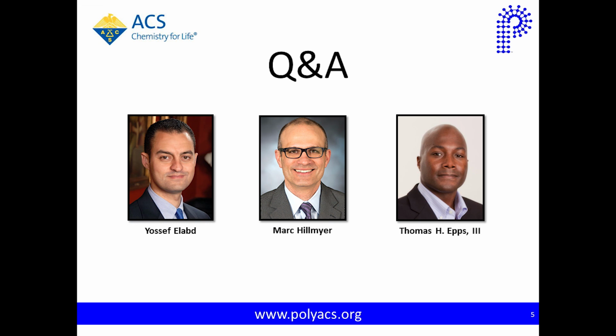Joe, here's a question from Elizabeth. She's interested in how the glass transition temperature of the backbone polymer can have a significant effect on ion conductivity in both homo and block polymers. You focused mainly on the methacrylate backbone. Do you have any comment on how that influences ionic conductivity? So, typically the glass transition temperature of the polymer scales pretty well with ion conductivity for these dry conductors. Basically what Thomas had in his presentation and the ones that I had with the fluorinated counter anions, they'll typically scale with the glass transition temperature, and you could also scale the conductivity as a function of temperature with this WLF or VTF behavior.